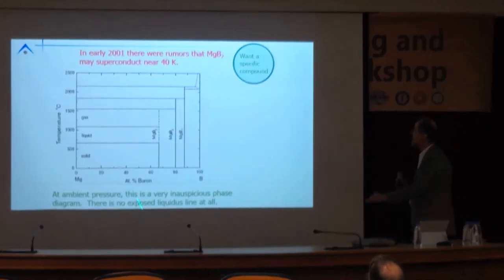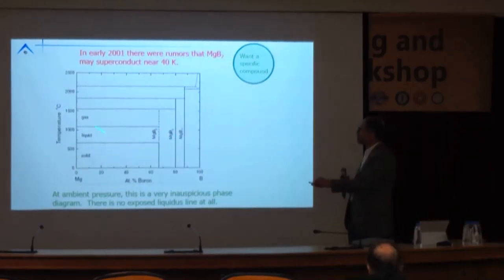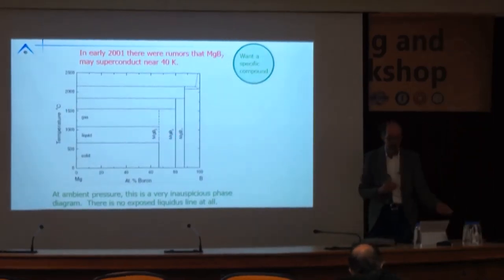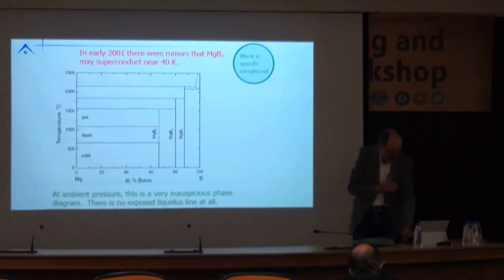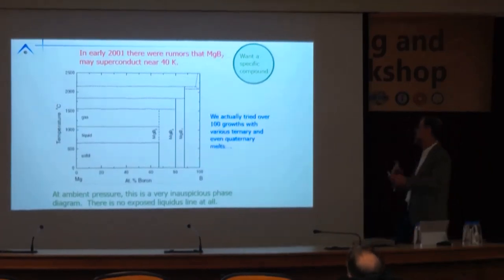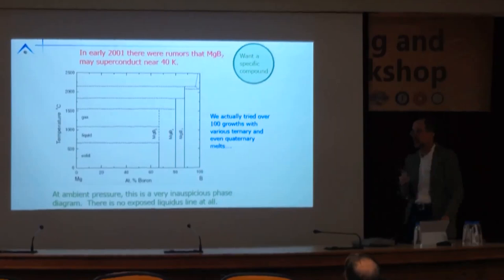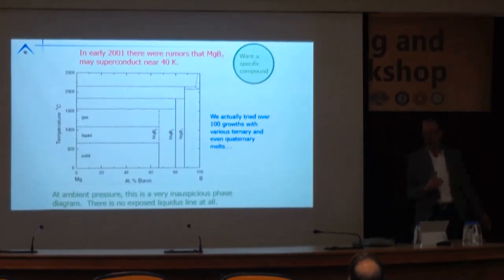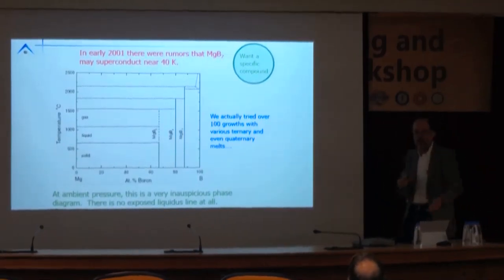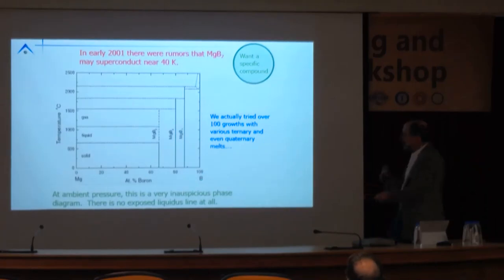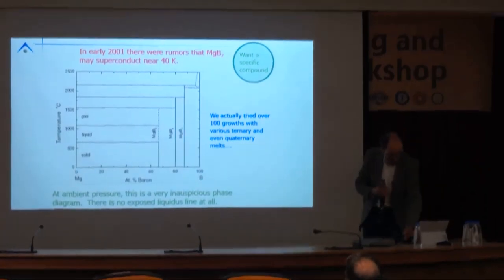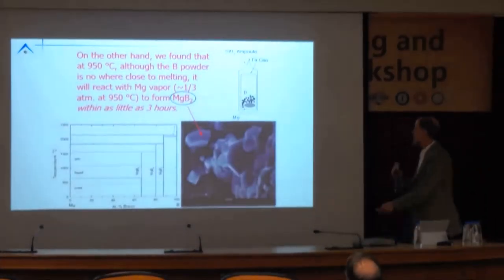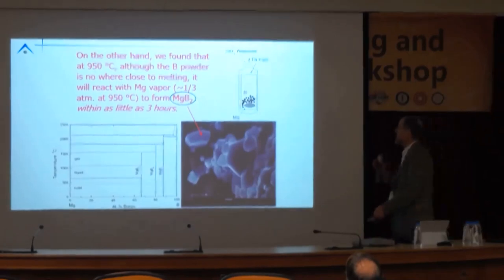You can look at the binary phase diagram. It is inauspicious. There is no exposed liquidus. It's not easy to grow single crystals. We actually tried hundreds of growths of binaries, ternaries, quaternaries. I used a kilogram of platinum. It didn't work. Okay? On the other hand, it can actually grow very nice high purity polycrystalline samples. And as a physicist, I'm willing to measure what I can get.